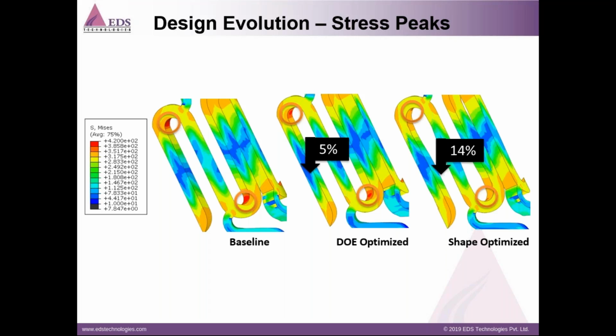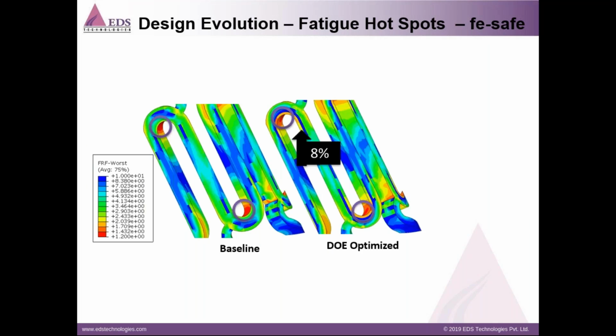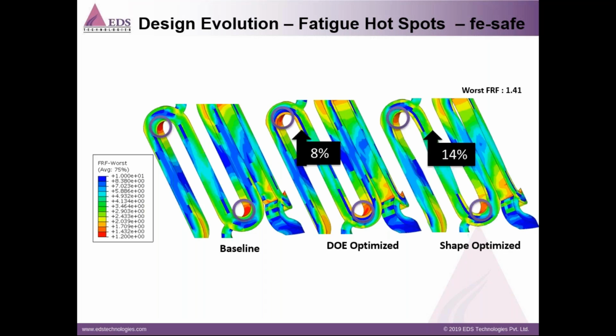We are also going to look at fatigue hotspot factors. Parametric optimization led to an improvement of 8% in the worst fatigue factor, and using the shape optimization, we have improved it by 14%. We started with a fatigue factor of 1.2 in this highlighted region, and we are ending up with 1.41 as the worst fatigue reserve factor, which is about a 14% improvement in the FRF result.